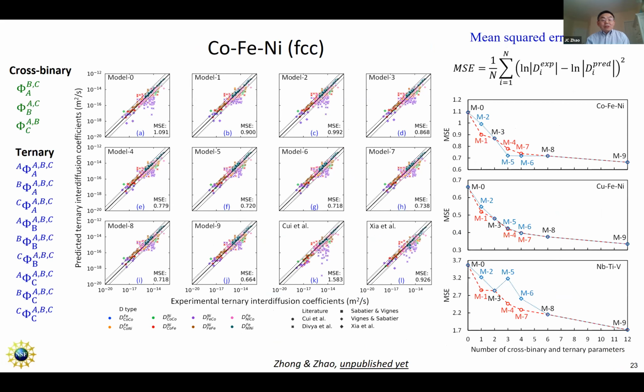So what we did was we went ahead and tested out various different combinations. The first thing we said, okay, we got this cross binary term, 3 parameters. We got the 9 ternary parameters, as I mentioned in the previous chart. So the first one is to take all of them to 0. That's model 0. Just extrapolate from pure binary without any interaction parameters for the ternary. And that's what the data look like. If you do a good job in binary, actually it's not too bad. If you compare with the previous literature assessments, it's better than one of the assessments, and slightly worse than the other, but not that much worse.